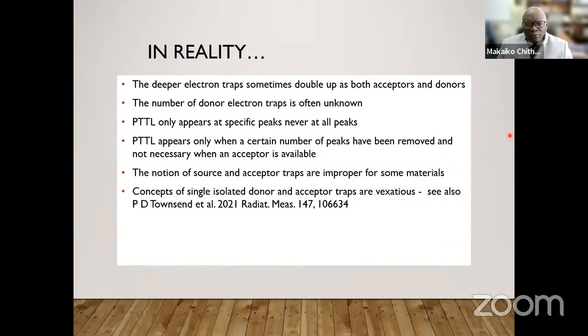Also, this talk of isolated donor and acceptor traps seems to imply that you have point defects that are isolated. But in fact, this notion of isolated point defects is a little bit problematic, because you always have point defects as aggregates. And in fact, in a recent paper in 2021 by P.D. Townsend, he went as far as saying point defects don't exist. Now, also the influence of hole traps on PTTL is something that should be considered. So in this slide, what I'm trying to do by giving all these facts is to state that the ideal doesn't always occur, although the ideal is useful when explaining a process.